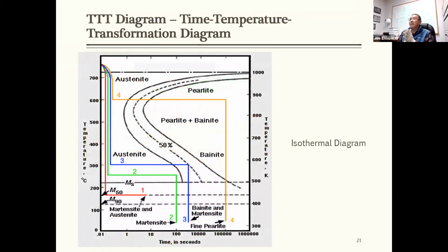The other diagram is called the TTT diagram, time-temperature-transformation. For certain microstructures, people like to heat treat slightly differently. They quench the steel down to a certain temperature, then hold it at a constant temperature and let the phase transformation occur, like the red line, green line or blue line drawn here. So they can perfectly control how much bainite and how much martensite will form in this steel. This is a different methodology for heat treatment.